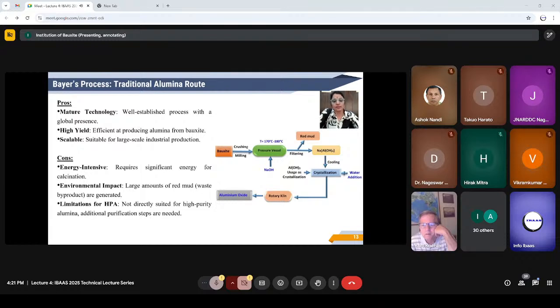So the Bayer process is highly mature with well-established infrastructure globally, and it is capable of large-scale production, but it does have some challenges. It is highly energy intensive, especially during the calcination step that requires a significant amount of heat. Additionally, it generates a substantial amount of red mud, which is an environmental concern due to its large volume and alkalinity. Another limitation is that while this process efficiently produces alumina, the purity level is generally not sufficient for high purity applications, such as semiconductors or LEDs.